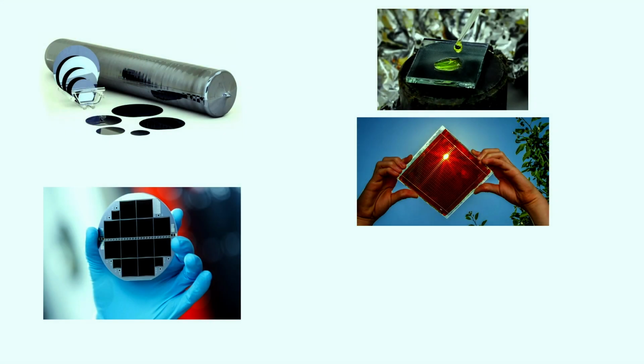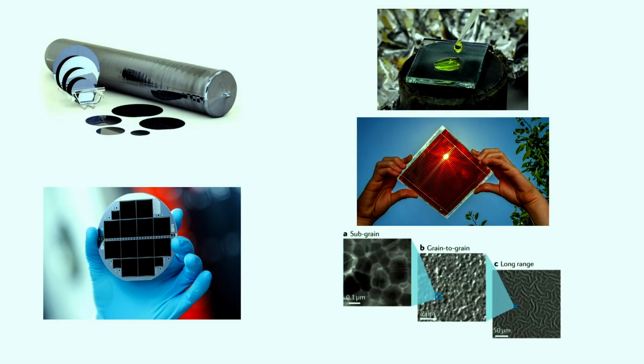This new generation of photovoltaics is challenging this paradigm by creating solution-processed materials where you can dissolve a few chemicals in a solvent, process it at maybe 100 degrees Celsius rather than 1500 degrees Celsius, and you're able to produce really nice photovoltaics. However, when you do this really quickly, you also create a lot of disorder. And this goes right the way from the atomic scale all the way up to the device level. And this has really important ramifications for both their performance and their long-term durability. And those things need to be solved if they ever want to compete with silicon, which is obviously this incredible juggernaut.